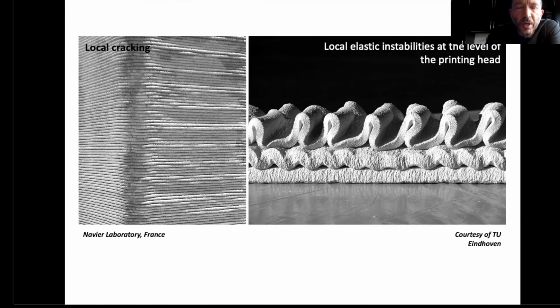So it means that the yield stress of the material must be high enough for the layer to have a controlled shape. At the same time, there is an upper limit because some artifacts or some problems do appear when you have a material that is too stiff. For example, if your stiffness is too high, you can have some local cracking in the sharp angles that are being printed, also local elastic instabilities at the level of the printing head if there is a slight difference between the extrusion velocity and the robot velocity.